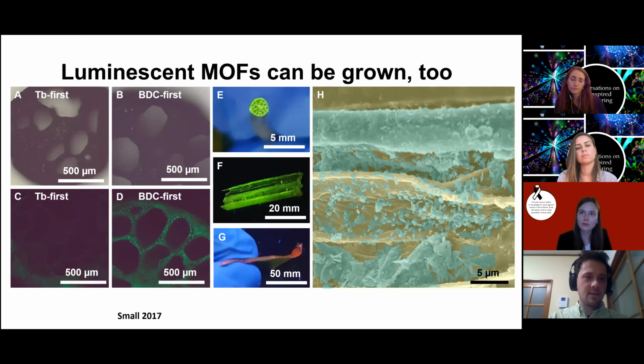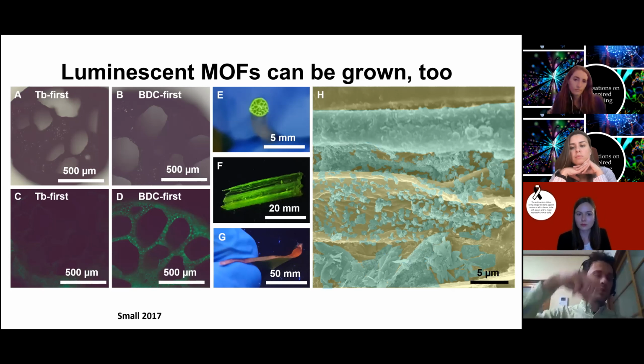So again, something that's not too typical in nature is fluorescence in plants, but we can see that if we put the terbium in first, we actually didn't form any MOFs, and that was because the terbium moved much quicker through these capillary forces than the large organic ligand, that benzene dicarboxylate, or BDC. But if we put the BDC first, it infiltrated for about 12 hours and then we switched it over to a terbium reservoir, we could get these nice platelet fluorescent MOFs growing throughout the inside and outside of plants.